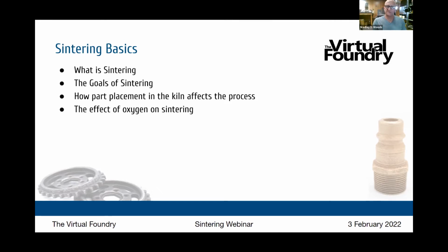So to combat this, in a large-scale $1 million industrial kiln, they would either vacuum out the atmosphere or they would fill it in with an inert gas like nitrogen or argon or whatever is appropriate for the metal that they're working with. We get around this process by adding carbon to the sintering environment. When it gets to the right temperature, any present oxygen will react with the carbon, it'll become CO2 and can no longer react with the metal. So this is how we deal with oxygen in our sintering process. It's very simple and elegant and interesting.